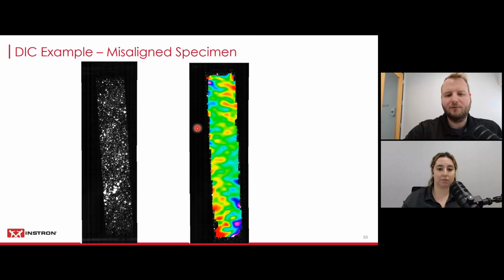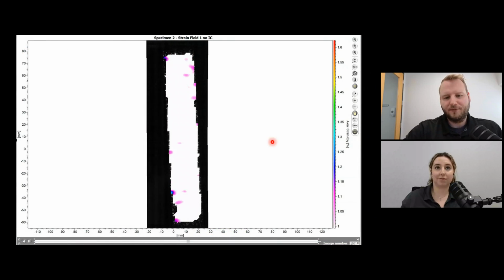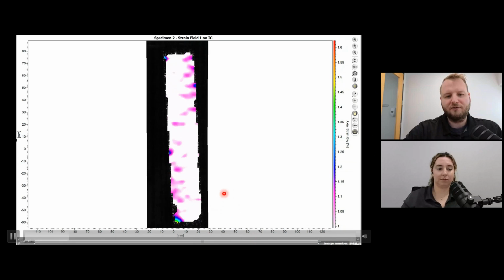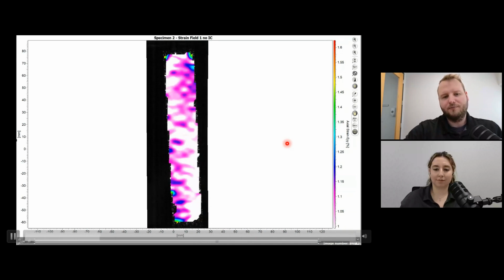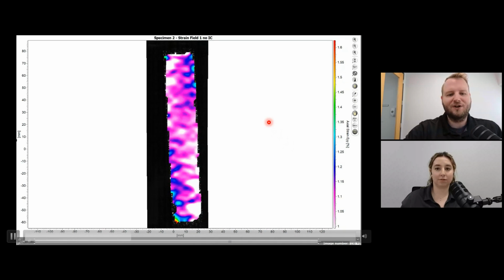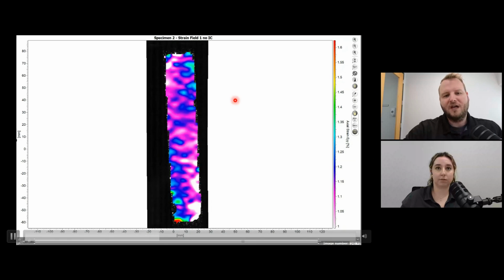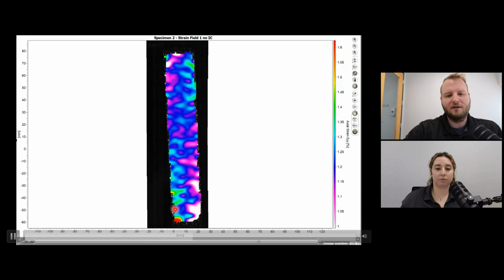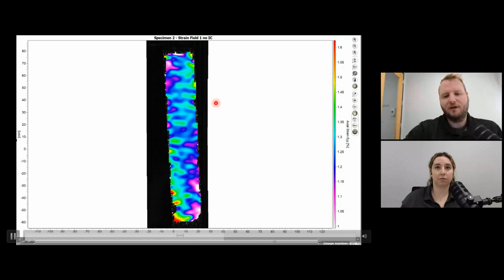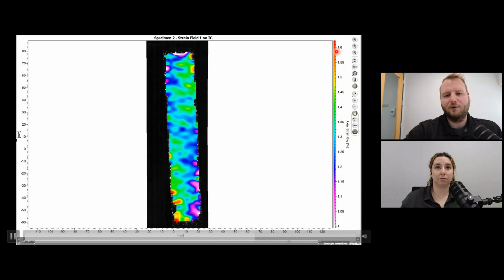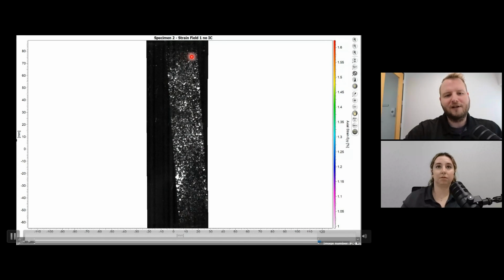We're talking about alignment a lot when we're testing composites, so we thought it's a good idea to give you an example of a purposefully misaligned specimen. You can already see it being a little crooked in the pictures. And you can see again here, generating that strain field from the point where strain was actually being put on the specimen. Those areas on the top right and bottom left are building up, and towards the end they turn red as we get to the 1.6% strain reading. At the end, definitely not a good failure here. It broke on both tabs. This is why alignment is so very important.